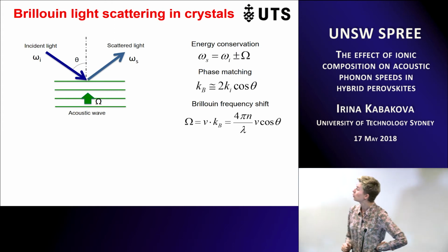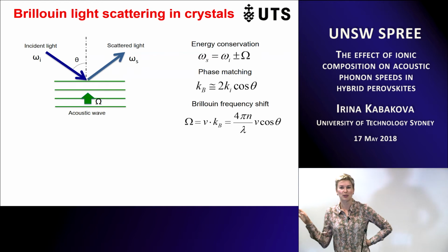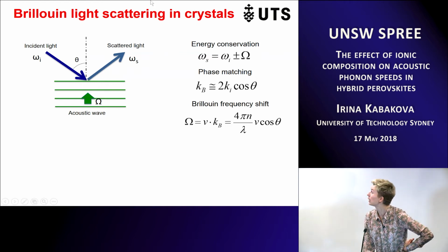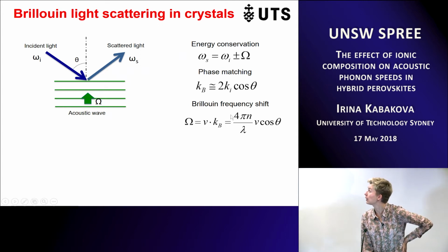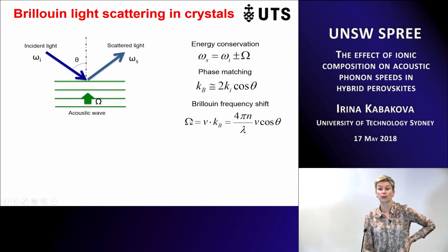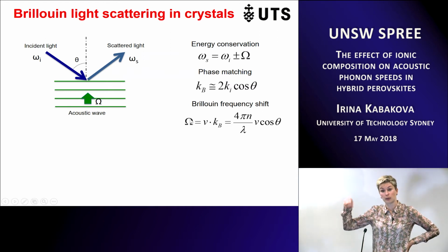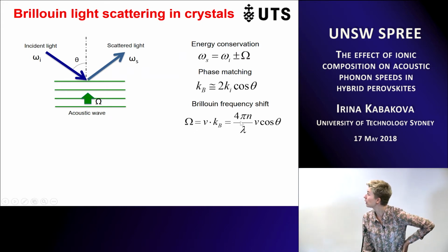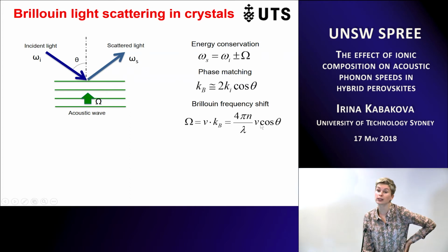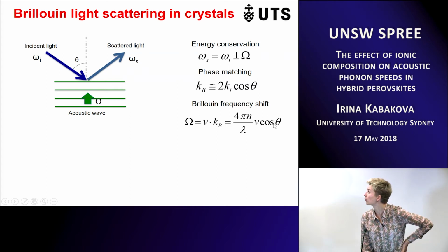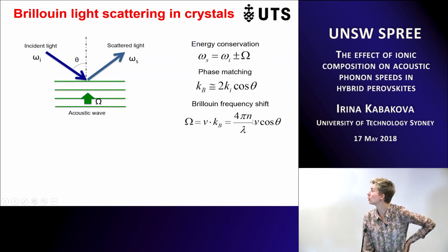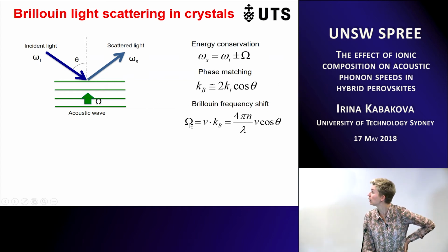So let me give you, it's perhaps the only slide with mathematics and expressions here, but nonetheless, due to energy conservation and phase matching, we can obtain an expression for the Brillouin frequency shift, so that's the shift which scattered light inherits after meeting with an acoustic wave. This frequency shift is proportional to the speed of sound, and depends on scattering geometry. There is this cosine of theta here, and there are a few properties of light, which are the wavelength of light and the refractive index inside the medium. But you can see that by obtaining the Brillouin frequency shift, we can directly find out the acoustic speed of a certain wave.